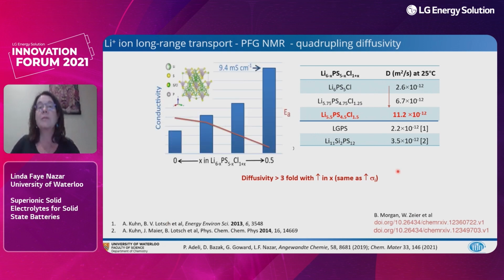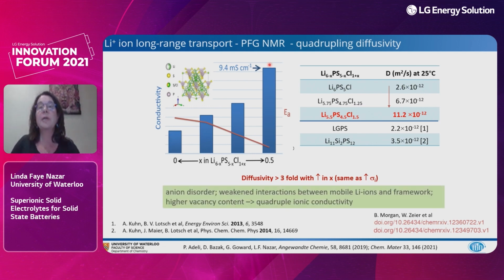And I guess what's important is that the diffusivity increases threefold, and that exactly marries with the increase in conductivity. And so we can conclude that anion disorder, that is the sulfide-halide disorder, and especially the weakened interactions between the ions in the framework, along with some extra vacancies, are what's responsible for a 3.5, or almost quadrupling, of the ionic conductivity.